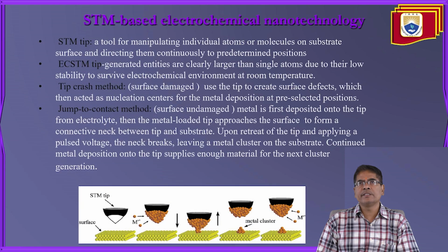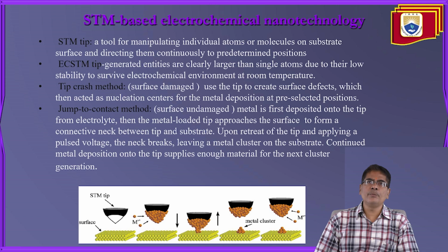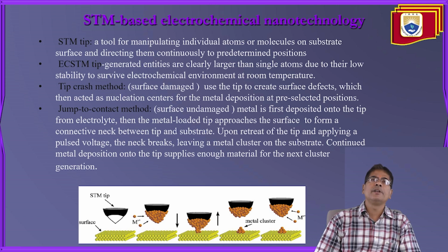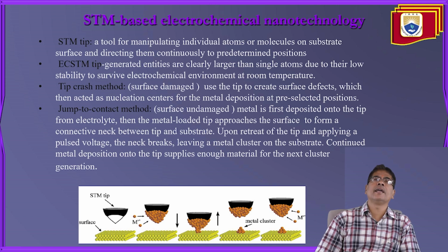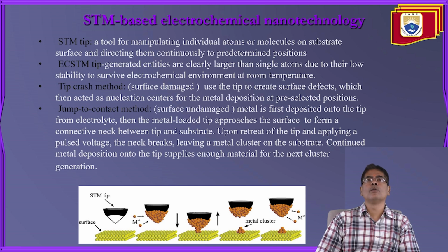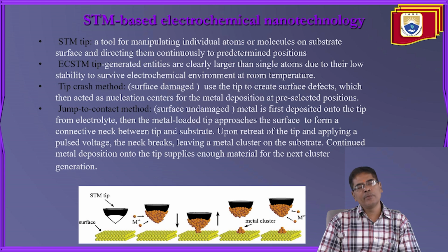So this is STM based electrochemical nanotechnology: the EC STM tip crash method and the jump to contact method. So these are the different STM based electrochemical technologies, right? This is a tool for manipulating individual atoms or molecules on a substrate surface and moving them continuously to predetermined positions. The generated entities are clearly larger than single atoms due to their low stability to survive the electrochemical environment at room temperature. In the tip crash method, the surface is damaged: the tip is used to create a surface defect, which then acts as a nucleation center for metal deposition at pre-selected positions.